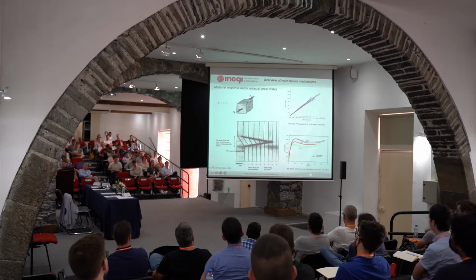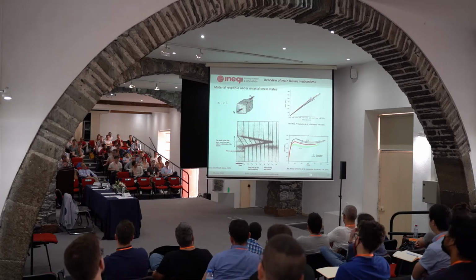If you look at, say, the shear stress-strain relation, these are some simulations that we have run and some experimental data that we have obtained for the resin, together with Miguel Bessa, who is currently at Brown University. You can see that in this region where the material is softening, we get additional waviness of the fiber. You don't have perfection in terms of fiber orientation, so you don't get a perfectly aligned fiber; you always get some defect, some misalignment. When you apply compression, that misalignment will increase and will further load the resin up to a state where you get this fiber bending and rotation. When the resin rehardens, you get this fiber lockup and bending until you get this kink band.